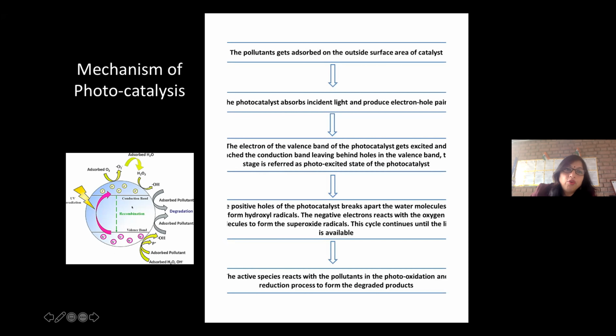So the issue of the photocatalytic material is when the electron holes are not separated properly, then the reaction will not take place, because holes react with water and convert that to the OH free radical, and then electrons react with the oxygen, forming superoxide ion free radical and making again OH free radical. Then finally it degrades the pollutants. So this is the mechanism.